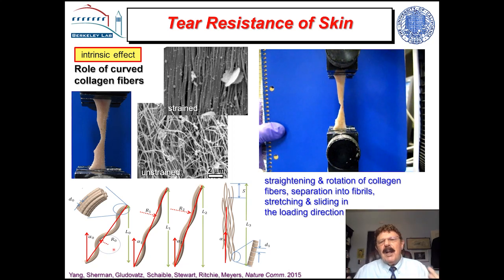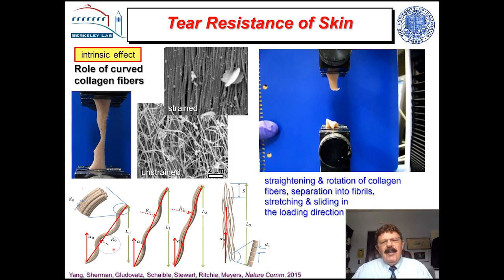And what happens when you put a load on skin? These collagen fibrils tend to straighten, and then they tend to rotate to carry more of the load. They've straightened and get into this sort of aligned situation, much like a polymer might, and then they stretch themselves, they separate and delaminate, and they finally fail. So you start off with a tangled mass of curvy collagen, and you end up with these aligned ones, which are really very effective in absorbing energy.